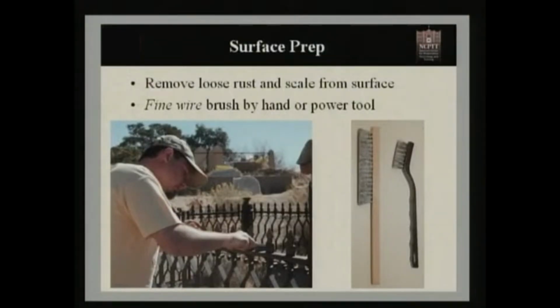Now the reason we say fine wire as opposed to heavy wire is for a couple of reasons. This can be done by hand, like the brushes that we see there in the photograph, or cup brushes or discs on a power tool, but we're talking about very fine wire. This does two things. The fine wire actually lasts longer. It is able to give and move with the brushing, with the treatment, and it is going to last much longer than a heavier wire that's going to break off and you're going to lose it and go through lots of them in one repair.